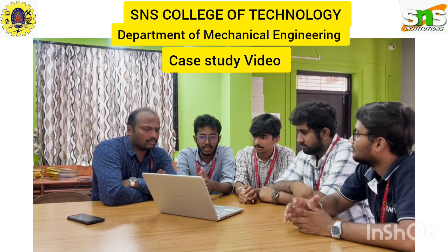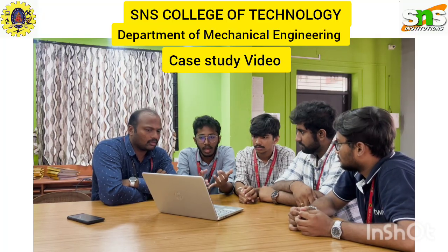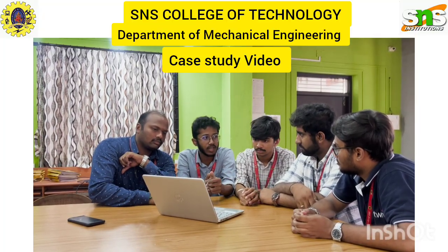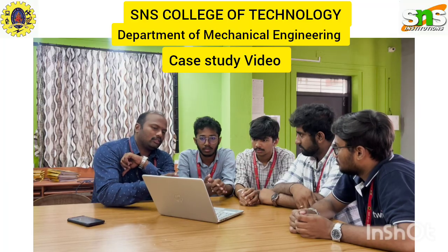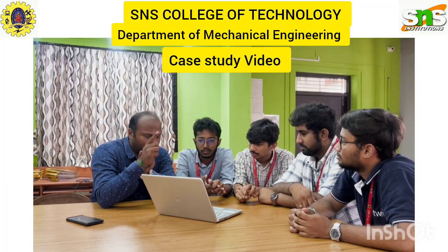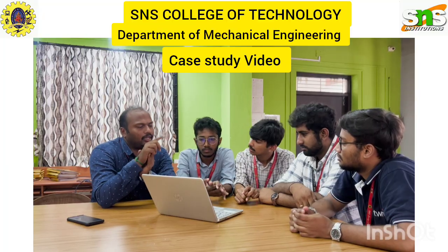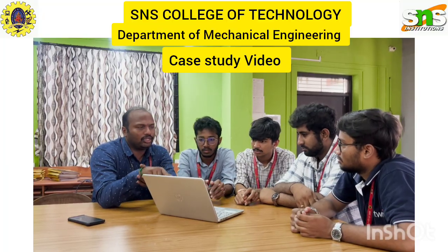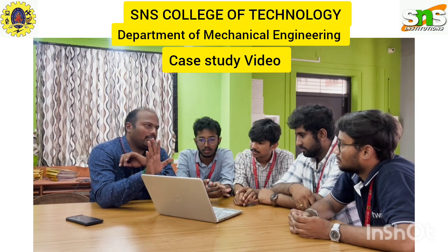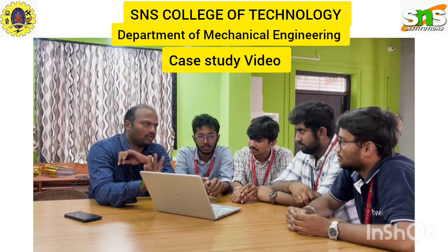While coming to the conclusion, the gear failed due to fatigue failure, as we concluded using this case study. This also occurs due to the hardness and case depth found in the gear, and some misalignment can also cause failure in this gear. Moreover, there is a formation of fatigue pitting and spalling, which is one of the main causes of the failure. Fatigue is one of the failures which occurs in high speed gearboxes. So this is the conclusion of the case study. Thank you.